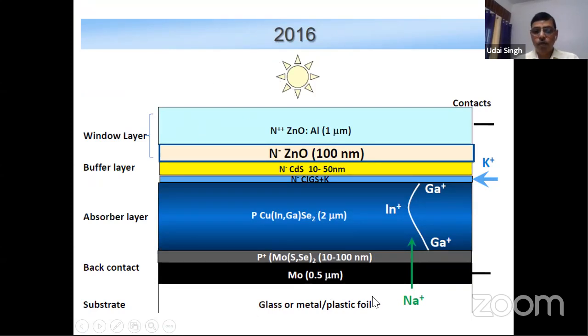You have a glass or metal or plastic foil, whichever somebody wants to start with, then you have molybdenum as the back contact. Then molybdenum selenide is generally formed between the copper gallium selenide and the moly during the process. So you have copper indium gallium selenide, which is around 2 micron. Then you deposit some alkali metals. Then you have the cadmium sulfide, then intrinsic zinc oxide, and then the top transparent conducting oxide. So this is the standard now being used. But still people are trying to play with certain other materials to enhance the efficiency, but there has not been much success on that. Lastly, in 2016, they had success in depositing the alkali metal and then annealing.